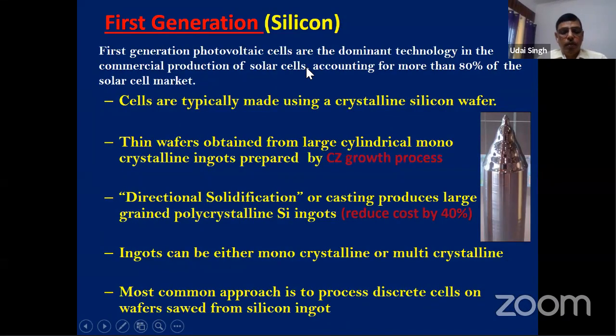So as I told, I will just go briefly through the silicon solar cells. Cells are typically made with crystalline silicon wafers, and these wafers are obtained from large cylindrical monocrystalline ingots. This type of ingot is grown by the Czochralski growth process, and then directional solidification or casting produces large-grained polycrystalline ingots. If you go for polycrystalline, it reduces cost by around 40%, but the efficiency becomes less. So ingots can be either single crystal, or monocrystalline, or multicrystalline. The most common approach is to process discrete cells on wafers cut from the same ingot. You saw it into different thicknesses.